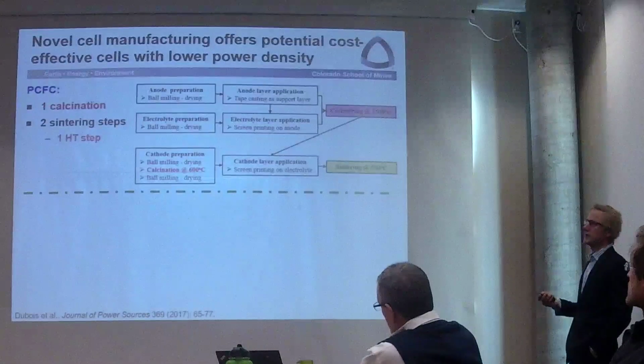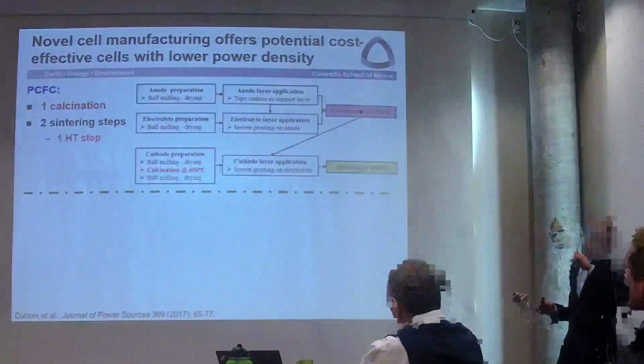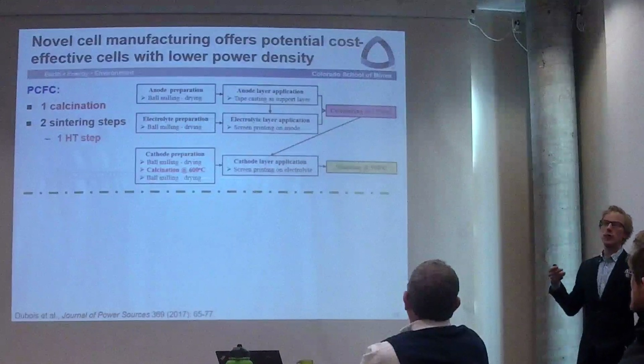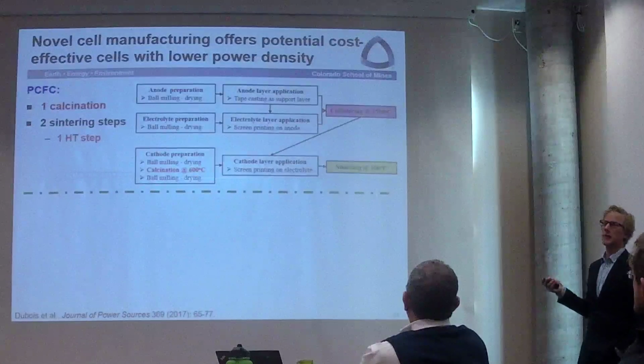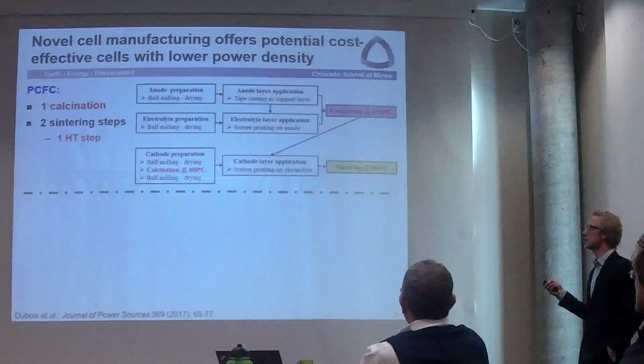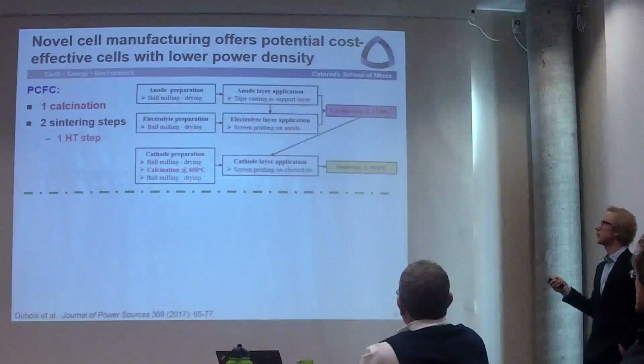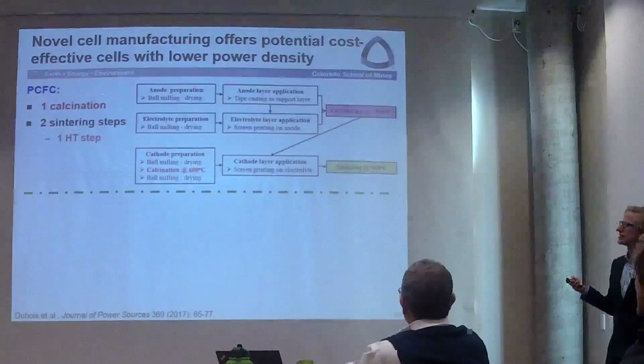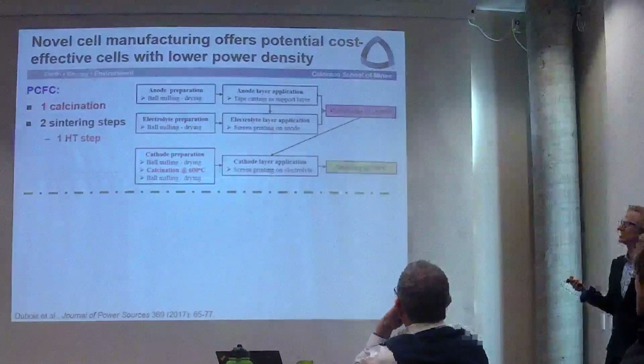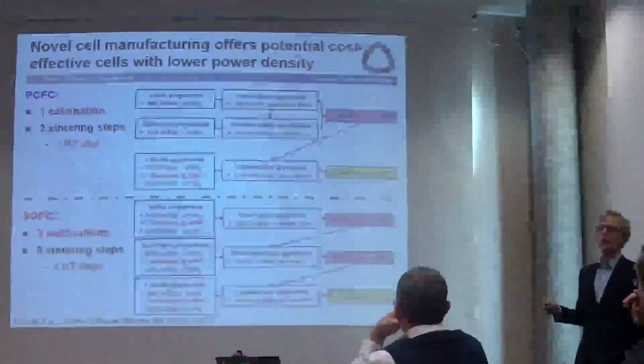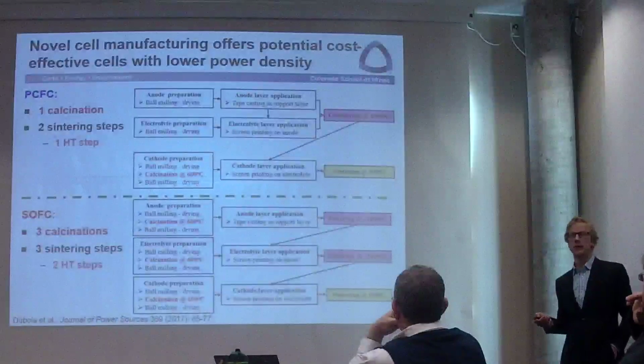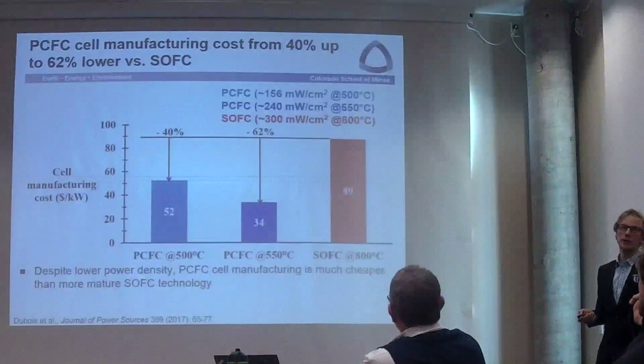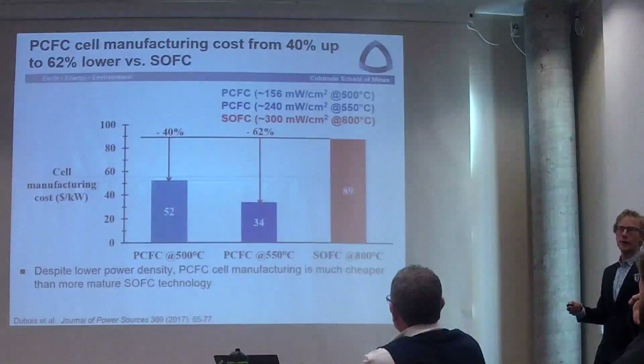So how is a PCFC actually made? Those materials allow to basically prepare the powder and sinter, preparation of the powder as well as the sintering application of the process. And we also only have one step for our PCFC, and then another 3 sintering steps for each layer application. And so that makes the numbers, we came to a very attractive conclusion, even though it's just a prediction and estimation.